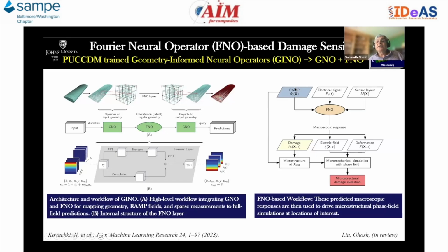So these are the three inputs. These are the ramp fields, the electrical signal, and sensor layout. Then you use the FNO-based neural operators to map the response fields, the full field of the response. And then once we have that, we can then use the damage fields together with the micromechanical simulations to probe the microstructural damage evolution.